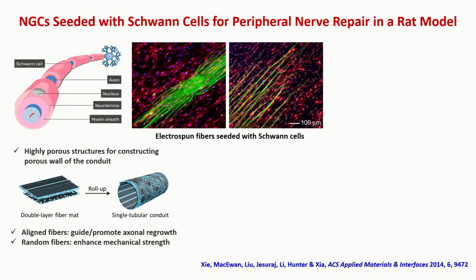And we are going to fabricate these conduits that can be used to bridge the two ends of the damaged nerve. We use this bilayer design at the beginning. We have aligned fibers, and then we have random fibers. We choose this bilayer structure for a reason, because you want your conduit to eventually have good mechanical strength too, not just the guidance for neurites, right?